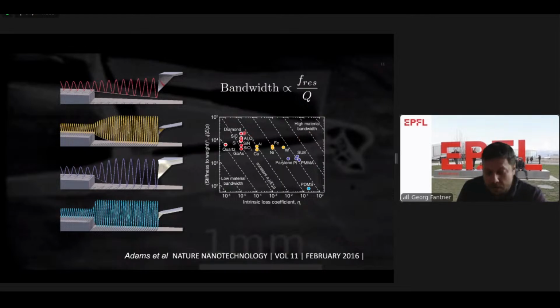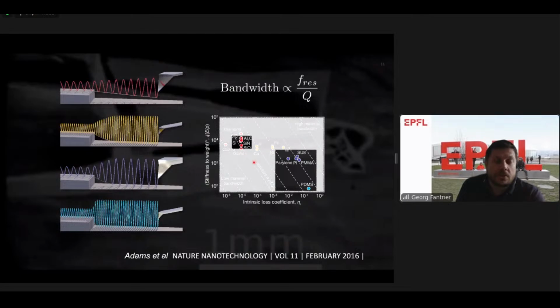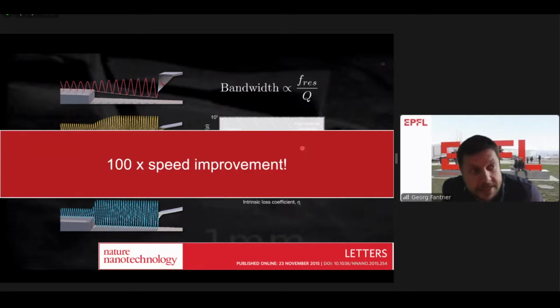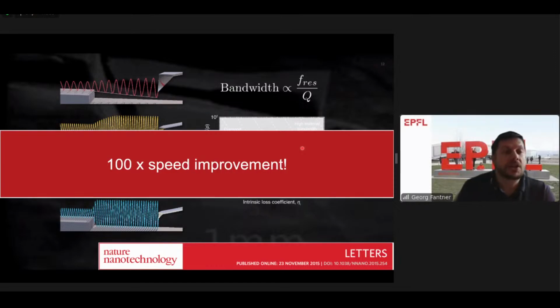And if we look where the normal materials are that we make cantilevers out of, silicon, silicon nitride, some people make them out of silicon oxide or quartz, we are in this regime here. But there's another group of materials that can be used for microfabrication that are 2 or 3 orders of magnitude potentially faster to make cantilevers out of. And so we picked that up a couple of years ago, and we've made cantilevers out of SU8, and we were able to increase the speed by a factor of 100 by just changing the material properties and optimizing the geometry.